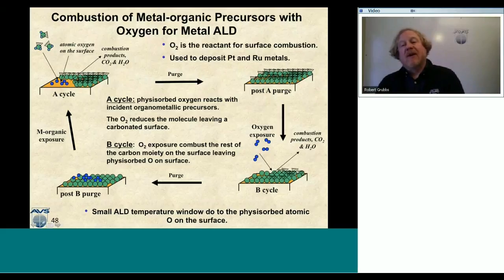But now that I've got this metal down here that is still in the oxidation state and it still has some sort of organic precursor on it. As I expose that organometallic precursor to oxygen, I actually react away all of that organic part of that precursor. I reduce that molecule down to its base metal, and I burn away that carbon and oxygen in terms of CO2 and water. But what's important to know is that this oxygen exposure will leave physisorbed oxygen on the surface. So here's some physisorbed oxygen on the surface, and that is a requirement in order for me to run the AB cycle to bring in the organometallic precursor to react with that physisorbed oxygen.